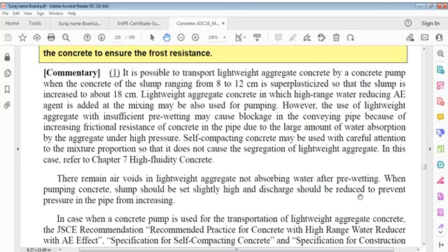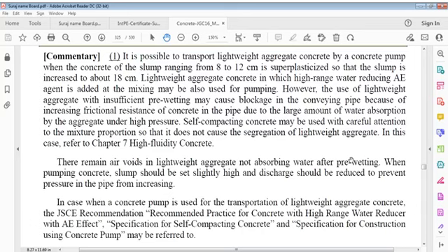It is possible to transport lightweight aggregate concrete by a concrete pump when concrete of slump ranging from 80 to 120 mm is superplasticized so that slump is increased to about 180 mm. Lightweight aggregate concrete in which high-range water-reducing air-entraining agent is added at mixing may also be used for pumping.